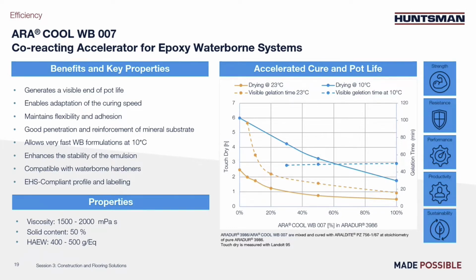When you look at the graph on the right, you can see on the left side the pure Aradur 3986 Araldite PZ 756-1 system. And going in the right direction on the graph, we substituted Aradur 3986 by the ARA COOL WB 007. They have similar H plus equivalent weight, so you can do that. You can see with the continuous line, the drying time at 23 degrees in orange or at 10 degrees in blue. The dashed lines are the visible end of pot life.